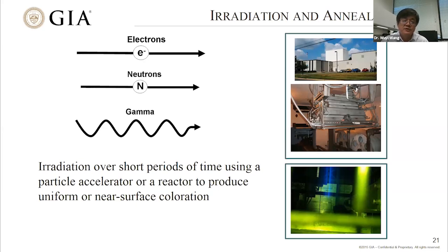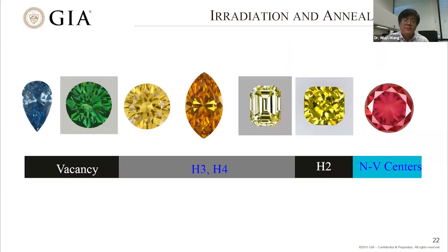When we talk about irradiation, the diamonds are irradiated with electrons, and the facilities are quite easy to locate all over the world. This slide shows the major colors that can be introduced using irradiation treatment. The irradiation treatment itself, without heating, basically introduces vacancies. We talked at the beginning about how vacancies introduce a blue color. So this is basically a blue color introduced by the irradiation.